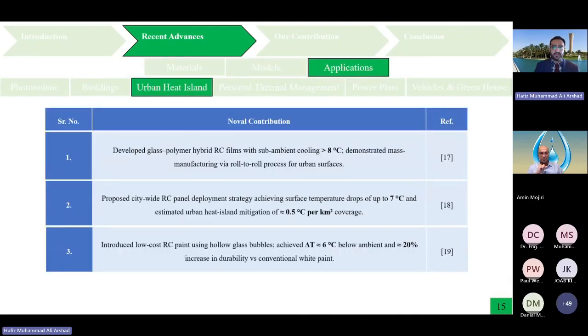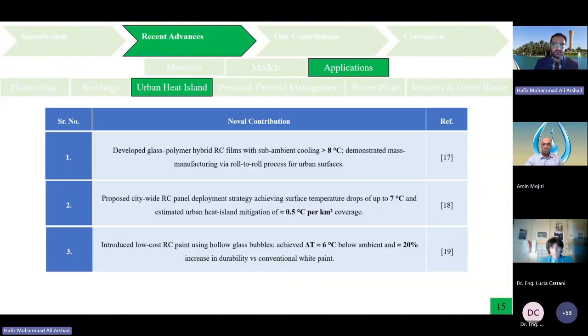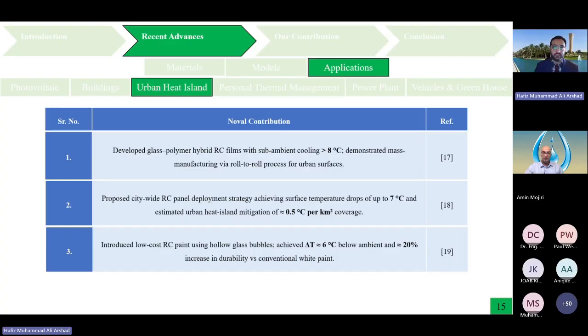So this is some of the data that we have collected from the literature. Here you can see that they developed glass polymer hybrid radiative cooling films with sub-ambient cooling of more than 8 degrees C, demonstrating mass manufacturing via roll-to-roll process for urban surfaces. Some other works proposed a city-wide radiative cooling panel deployment strategy, achieving surface temperature drop of up to 7 degrees C. And some other works introduced low-cost radiative cooling paints using hollow glass bubbles, achieving almost 6 degrees C delta T, which was almost a 20% increase in durability versus conventional white paints. So this is some of the literature that we have collected, but our focus was on air water harvesting.